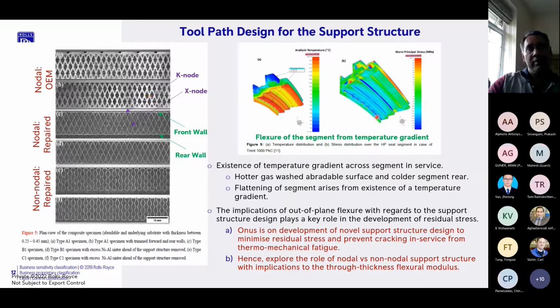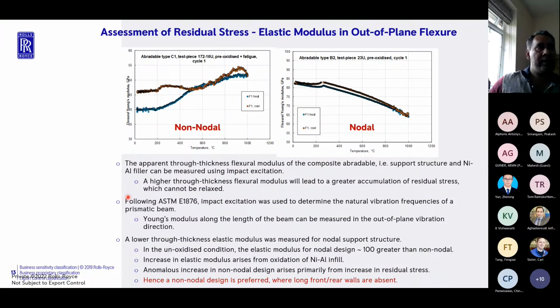The point to note here is that during service, this segment flattens and unflattens. So one of the ways in which you can define a criterion is by looking at the elastic modulus. If you look at the elastic modulus of this abradable in out-of-plane flexure, because it's clearly flexing in and out of plane, then that may be a very useful test in ascertaining whether it's possible to go from, say, a nodal design to a non-nodal design in order to increase the life of this abradable. So that's exactly what we did.